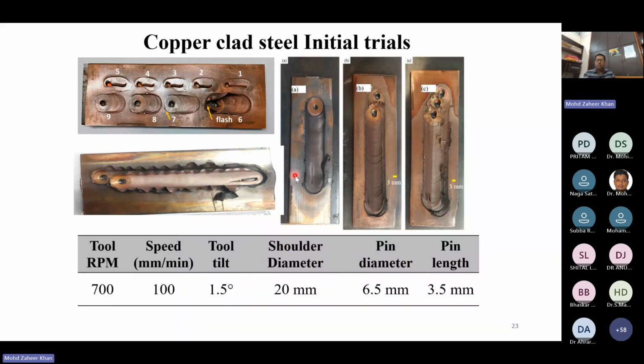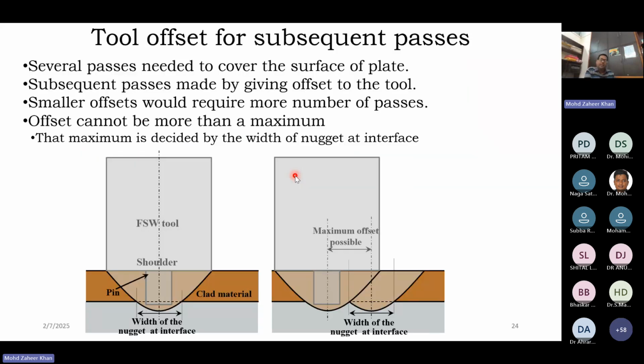So therefore, there is another parameter that has to be set, which is not required in the case of welding, but here it is very much required. That is the tool offset for the subsequent passes. So if one pass is made, then for the second pass, the tool has to be moved in the left or right direction. So to estimate what should be the amount by which the tool has to be moved or offset, we made this simple schematic diagram, and we can guess this thing.